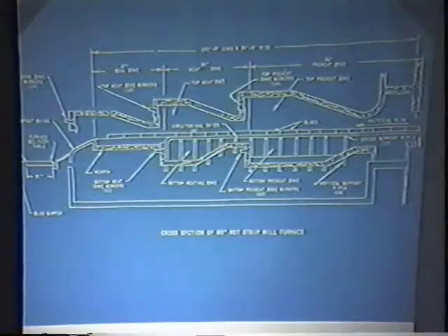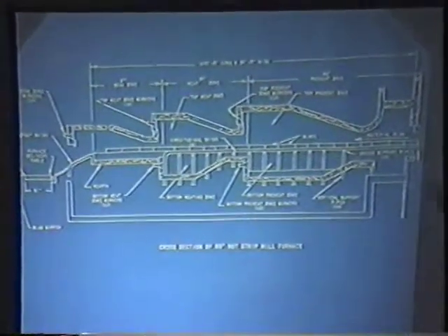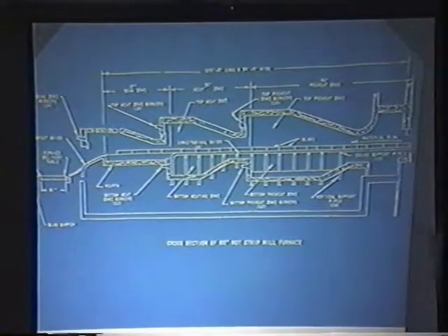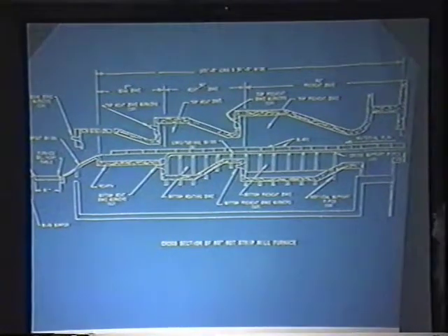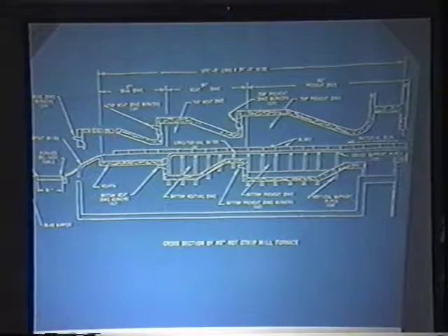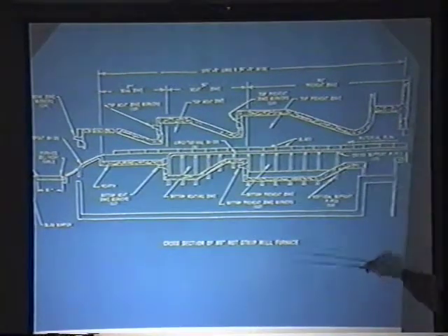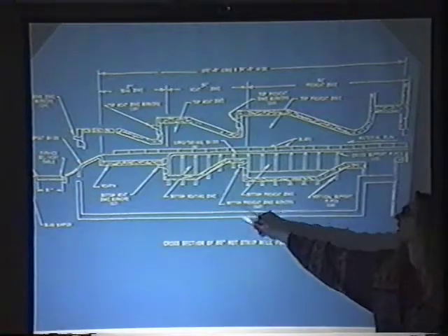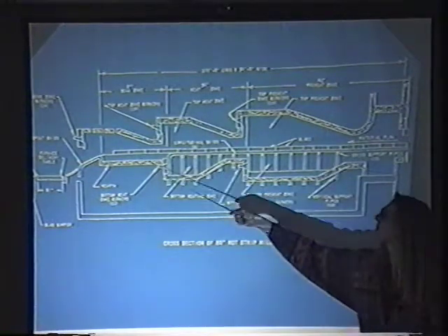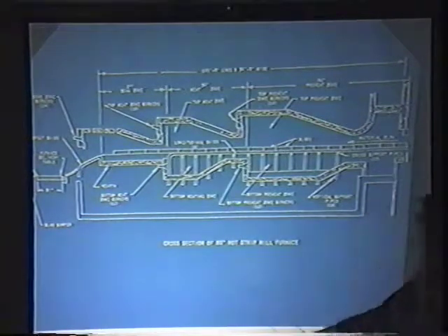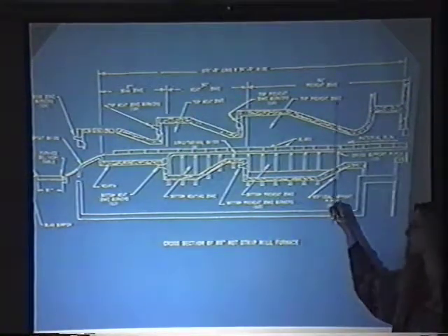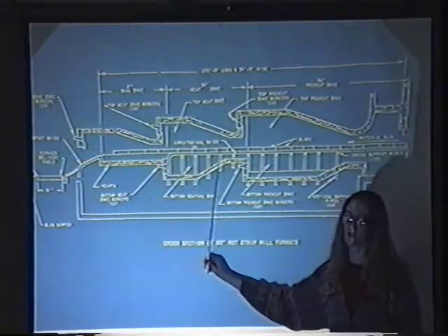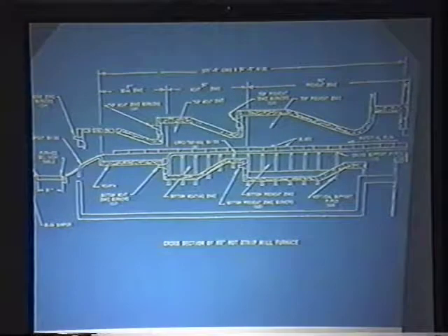Here is a cross-section of one of our reheat furnaces. The material is flowing this way, as shown by the arrow. This is the back end where we push the slabs in. These furnaces have 5 reheat zones: the top and bottom in the preheat zone, top and bottom in the heat zone, and then one area here in the soak zone. This area of the furnace is 2100 degrees, and these 2 areas are 2300 degrees, and that's to make sure that all the microalloying elements are fully back into solution in the slabs.